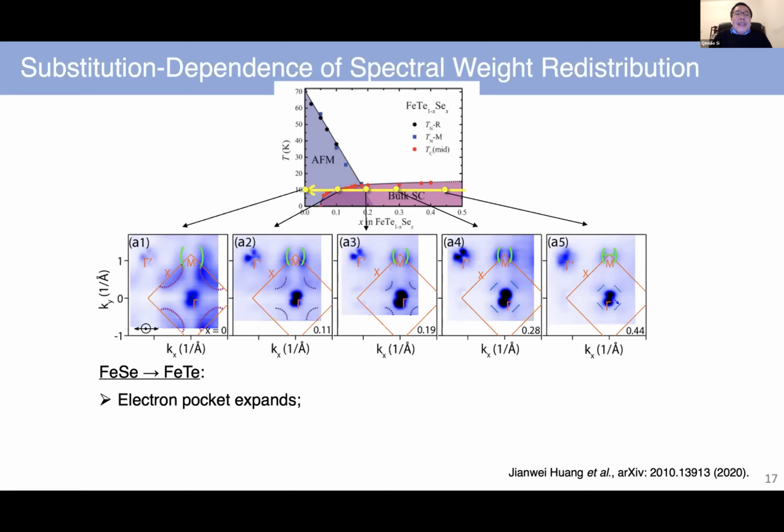The advantage is that something like dz square you can really track. So there's some well-defined analog of what we call the SPD states of the heavy fermions that you can zoom in on, and they spend a lot of time looking at it, and it turns out that's extremely illuminating. In other words, you can look for hybridization and its breakdown near gamma, and experimentally it's very hard, and there's some feature that's there. It turns out the breakdown of hybridization is just in your eyes if you look at the right place, which is near X, where the dz square crashes down or not, depending on whether the hybridization is there or not.